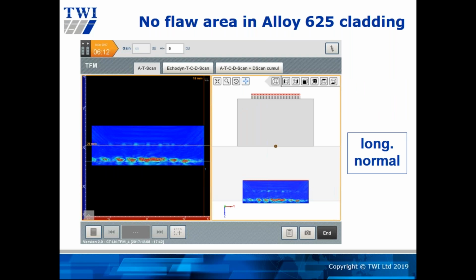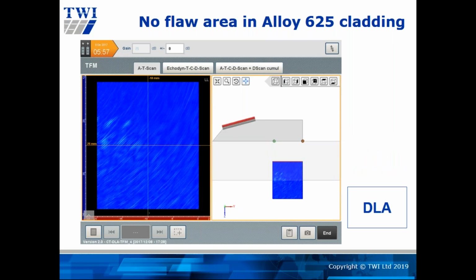Similarly, if you had an image such as this, there is a requirement for the operator to look at every point within the cladding in order to make sure that there are no indications. So even though the signal to noise is better, there are a lot of signals to analyze. But once you move to the second technique, it's simply a case of, is there a flaw or is there no flaw? Being able to improve these inspections in this way, I'll talk about it a little bit later, you can implement rapid inspection programs for cladding, not just cladding after it has been deposited, but in fact cladding while it is under deposition. So this is the kind of developmental area which is currently ongoing.